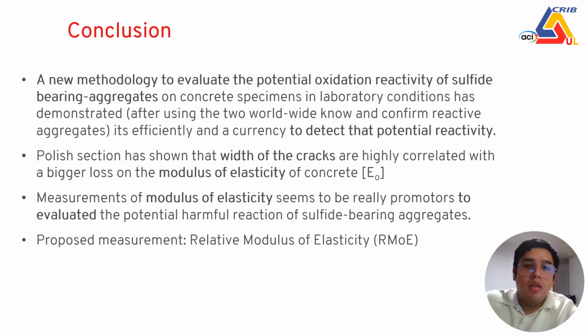In conclusion, this new methodology can evaluate the potential oxidation reactivity of sulfide-bearing aggregates under laboratory conditions in a shorter period of time, and the polished section showed that the width of the cracks is highly correlated with a bigger loss of the modulus of elasticity. Also, measurements of the modulus of elasticity are the best parameters to evaluate the potential oxidation reaction of sulfide-bearing aggregates, and the proposed relative modulus of elasticity can really distinguish between a reactive and a non-reactive aggregate.